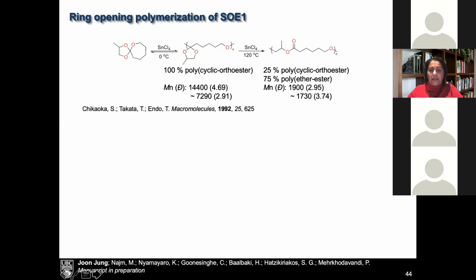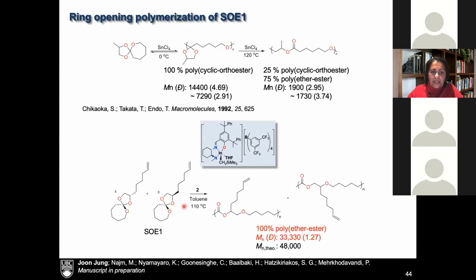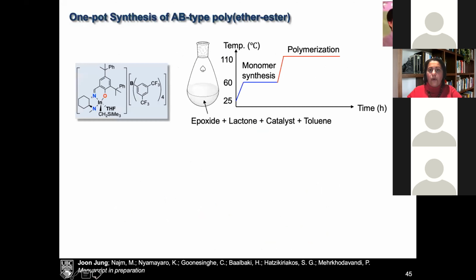And then what he showed was that if he took these spiro orthoesters that he generated, purified, and polymerized them with this catalyst at a different temperature, so he made them at 60 degrees, if he took these materials at 110 degrees, they polymerized, and they polymerized to form these beautiful, perfectly alternating AB type copolymers. And so the question became, why can't we just have a situation where we can switch on polymerization by making the monomer under these conditions?